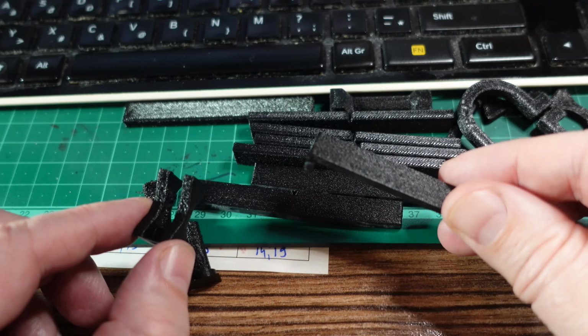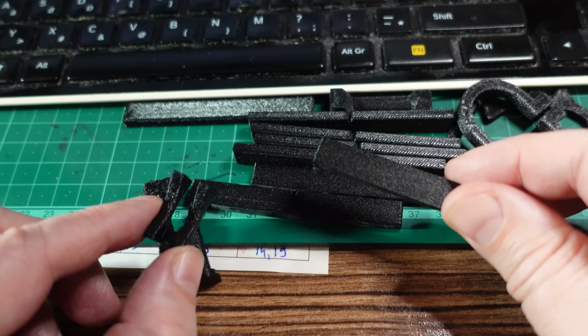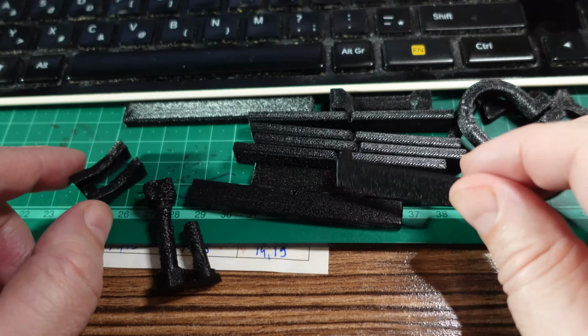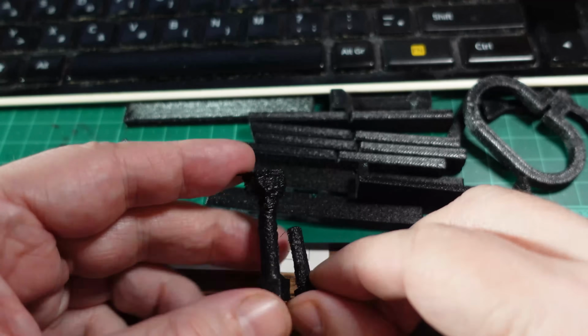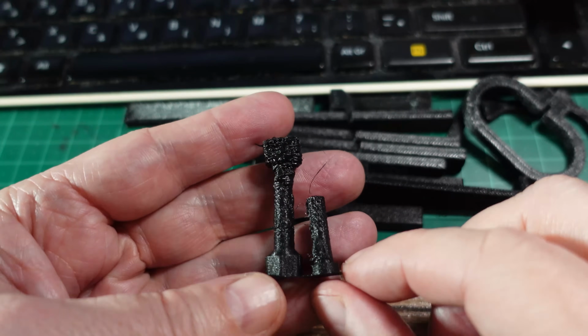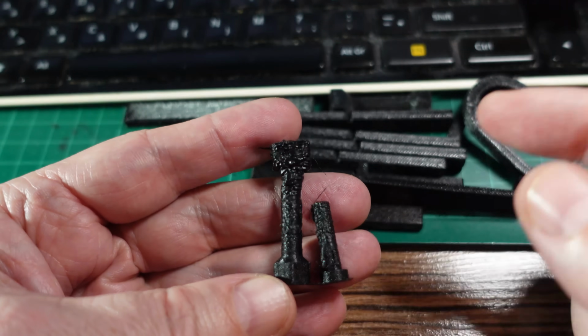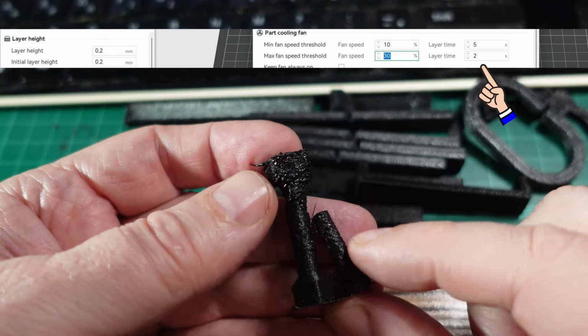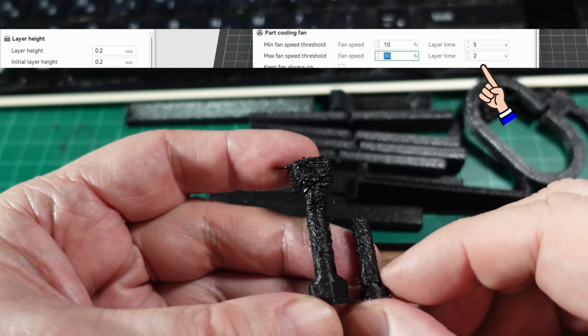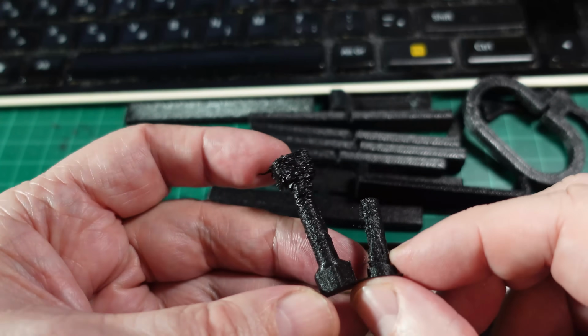This time the print quality is on the edge of acceptable, but definitely I can see that it needs more drying. Well, except with this object here the surface quality is very bad, but not because of the moisture. Well, actually it is partly, but I should increase the layer printing time. But without further drying, I just don't want to invest more energy into this filament.